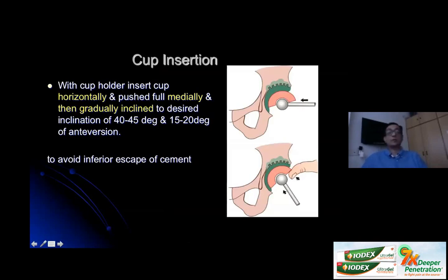Take the cup on your cup holder if it is of a smaller size, and then first introduce it horizontally and medially so that it rests on the towel, and then gradually incline it to the desired position, about 40-45 degrees of inclination and about 15-20 degrees of anteversion. By doing this, you prevent the escape of the cement inferiorly, and you get a very good cement mantle all around the cup, and you will have a good cement mantle in all the 3 zones.